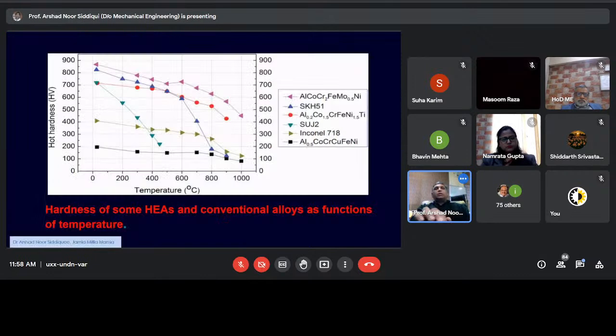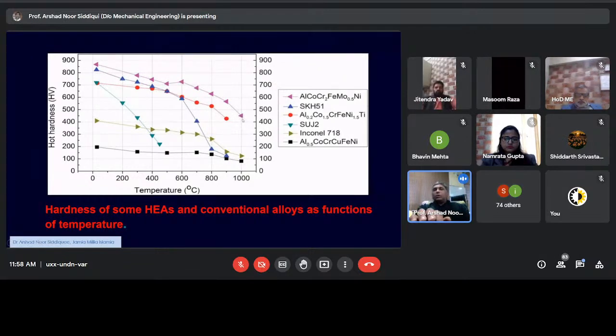So this is a quick reference of how high entropy alloys are placed vis-a-vis high temperature strength. You can see that if you increase the temperature from room temperature to as high as 1000 degrees Celsius, they hardly see a 40% drop in their hot hardness. Even at 1000 degrees Celsius, they show approximately 450 to 460 HV hardness, which is approximately the room temperature hardness of bainite. So it's remarkable in terms of high temperature properties.